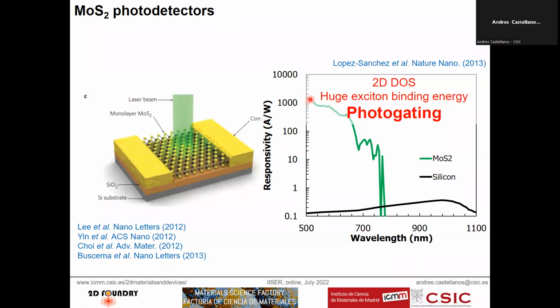Why do these two-dimensional semiconducting materials have this huge responsivity? There are many reasons. One is that these materials have a density of states that has discrete jumps. So you have some resonances. This is standard for any two-dimensional material. Instead of having a continuous density of states, you will have a stepwise density of states. These transition metal dichalcogenides have a huge exciton binding energy, so they have a strong light matter interaction.